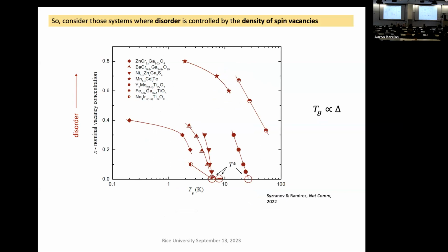Now, the reason this train of logic had not occurred previously is that the whole community, literally for 30 years, thought that all of the spins were involved in the spin glass state. And there was no requirement to calculate what the freezing temperature was, because no one can calculate that for a regular spin glass anyway. So it was just this big cop-out. And everybody assumed that all the spins were in the spin glass state. And we know that cannot be true, because in the pure system, there's an energy scale.